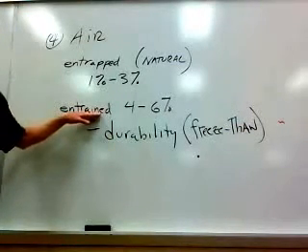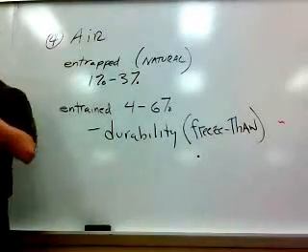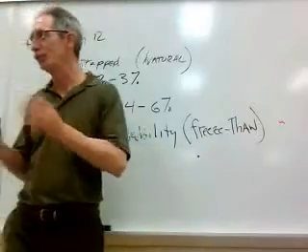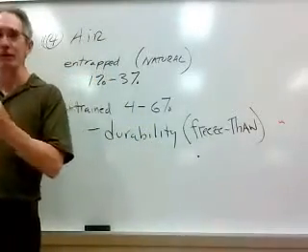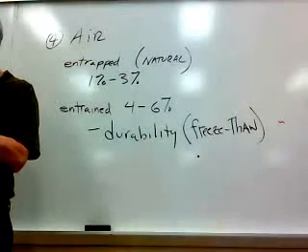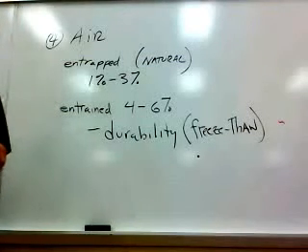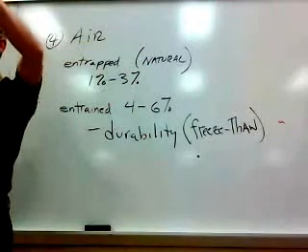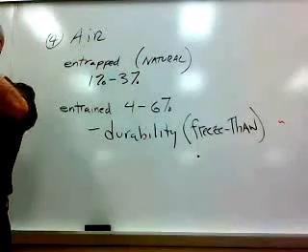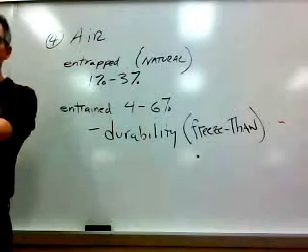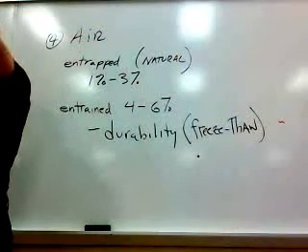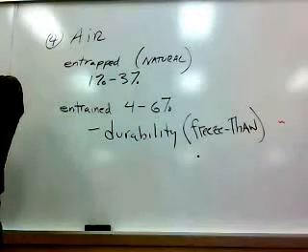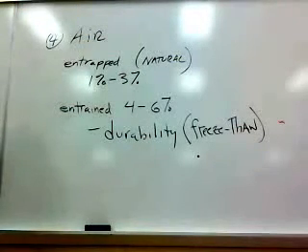Adding more air into it gives the hardened concrete extra little chambers, so that if water's going to freeze, maybe it's not just pushing on hardened concrete. Imagine, if you will, I'm this molecule of water, I'm going to freeze, I'm going to get 11% bigger, but now over here and over here and over here, I've got a little extra space to expand into.